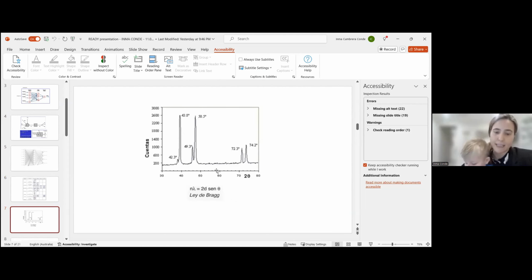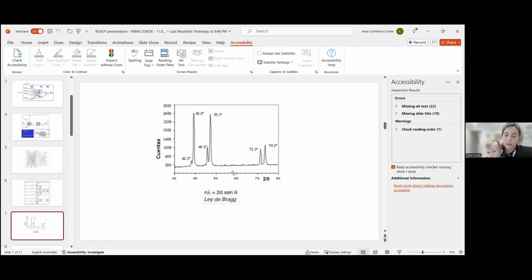Here you can see what is called an X-ray diffraction. So our source of information can be seen here. This diffraction spectra satisfies what is called Bragg's law. In this spectra, the wavelength is monochromatic and known. The angular positions of the diffraction peaks provide us with the Bragg angles. Therefore, they allow us to determine the other variable, known as interplanar spacing or interplanar distance. The problem of reconstructing the Bravais lattice from a few dozen interplanar spacings is actually of great complexity.